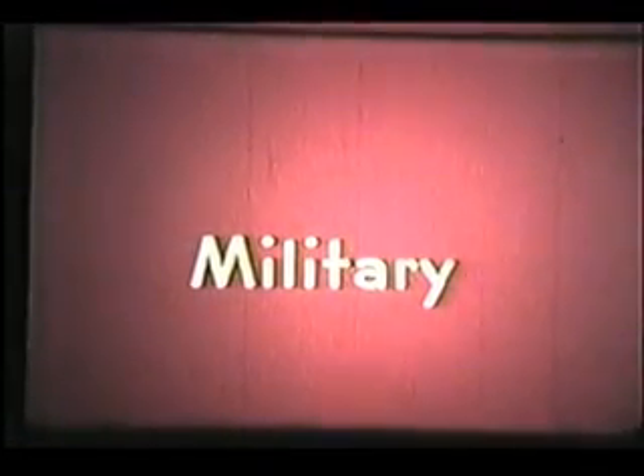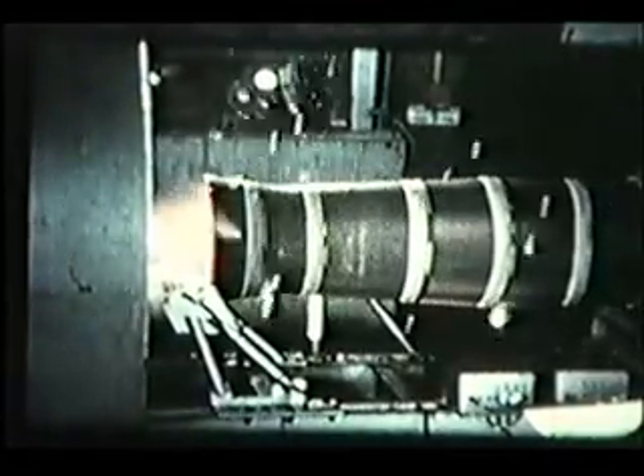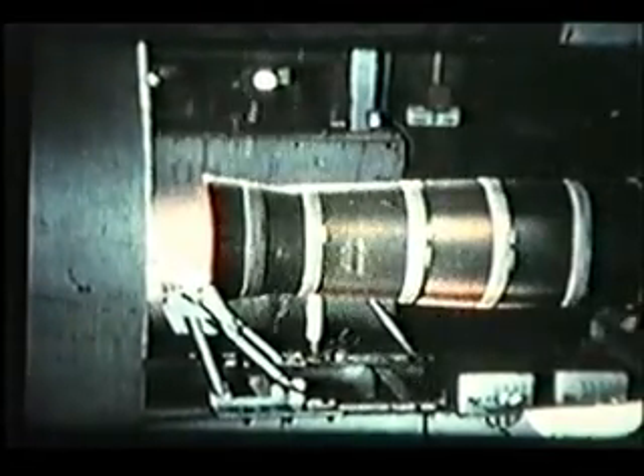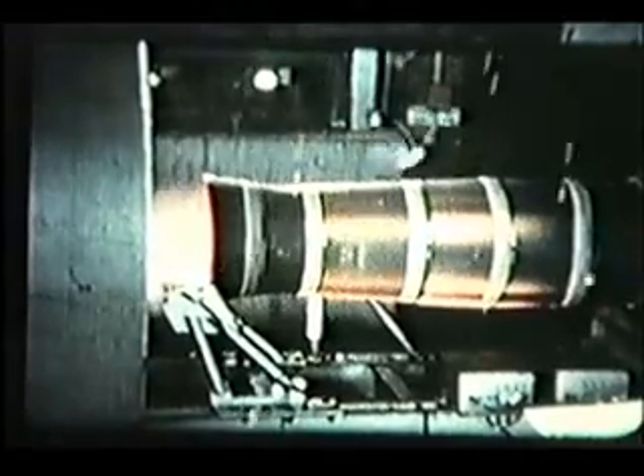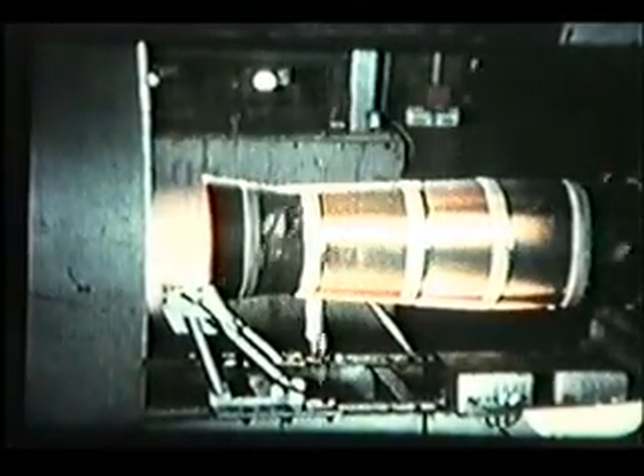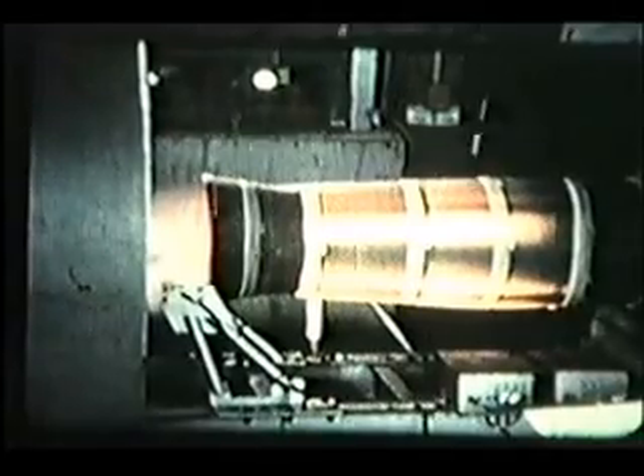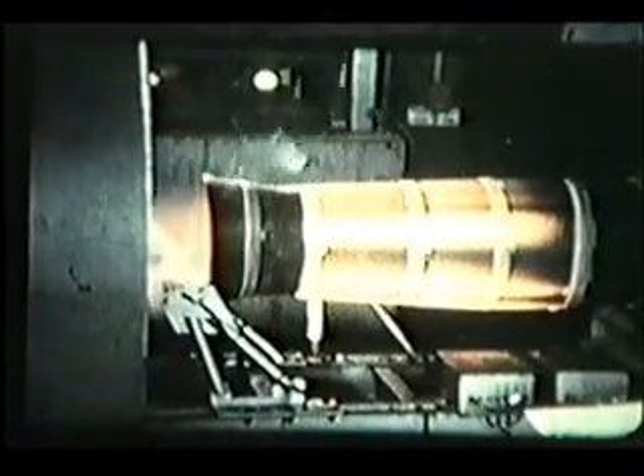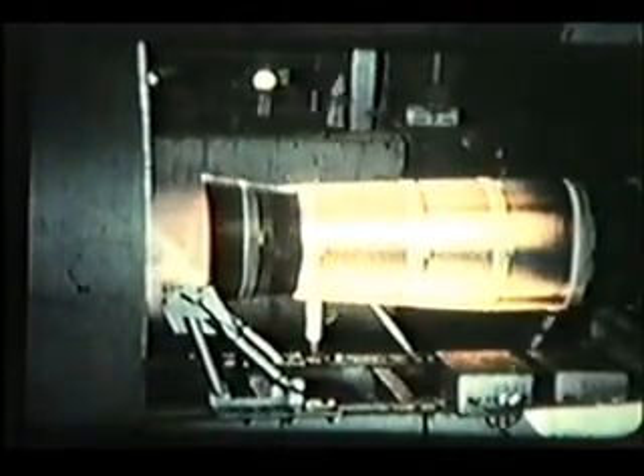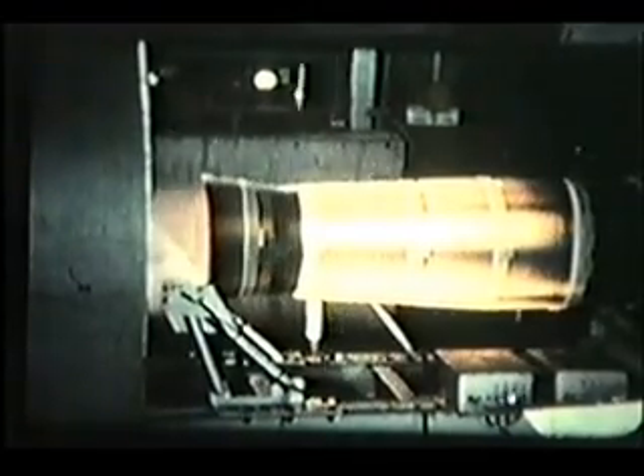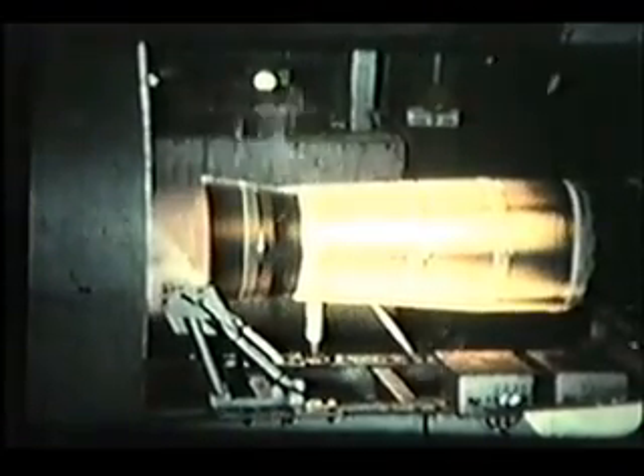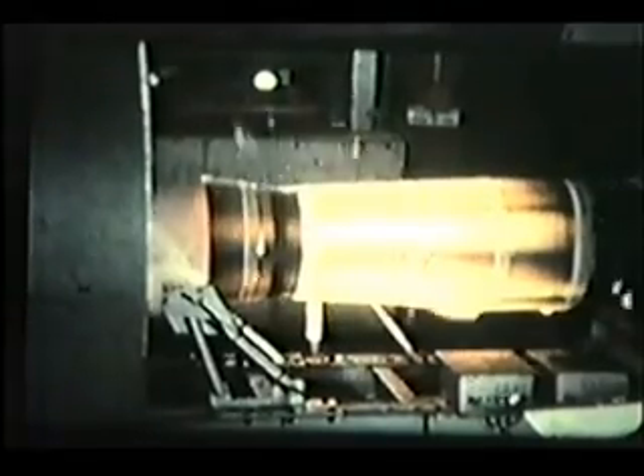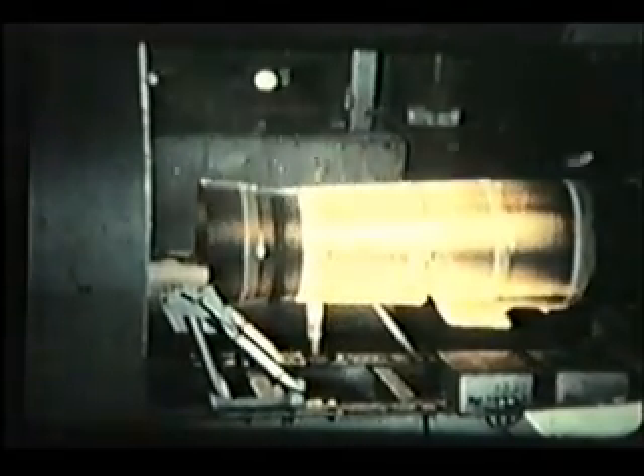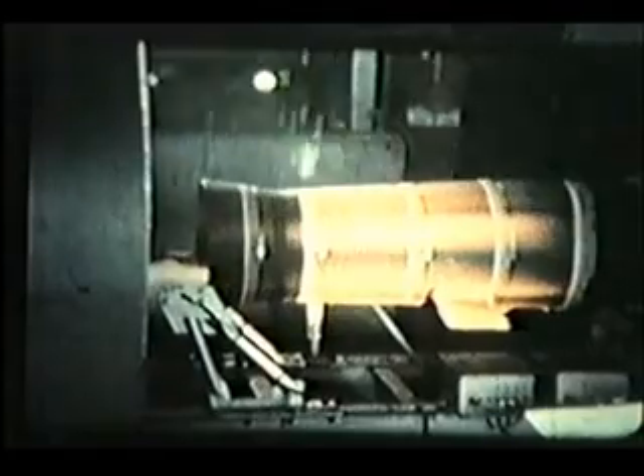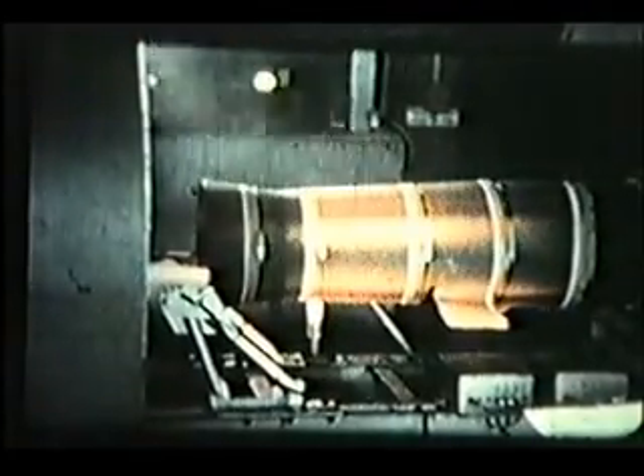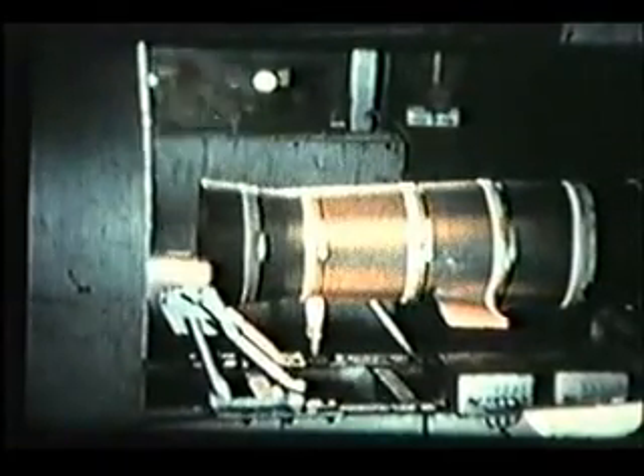Rokide has been particularly useful for protecting of missile nozzles and ramjet chambers for the military. 2 static tests of a 7-foot by 29-inch diameter ramjet engine produced by the Marquardt Aircraft Corporation are shown. Here it is fired with liquid fuel without the protection of Rokide on the ID surfaces. The metal is unable to withstand the 2200 degree F temperature and erosive forces of the high-velocity gases, and premature failure occurs at 14.2 seconds. In the second test, you will note the substantial flexing of the engine at the left-hand end as the combustion starts.